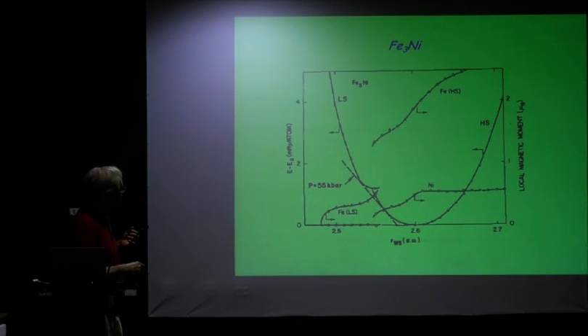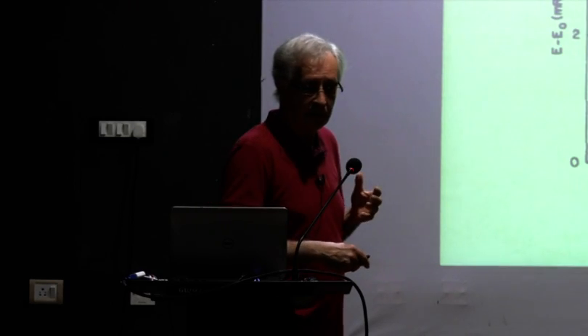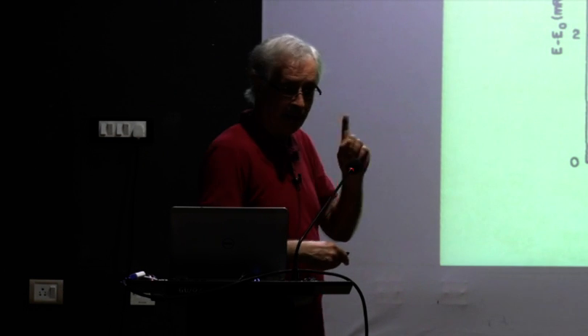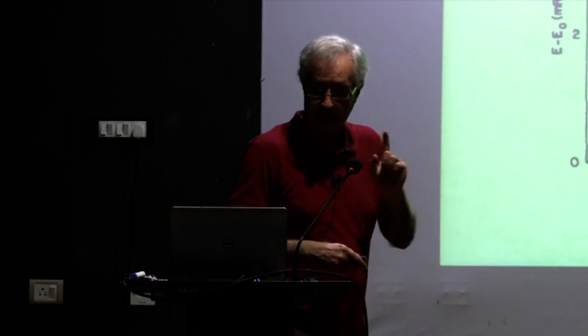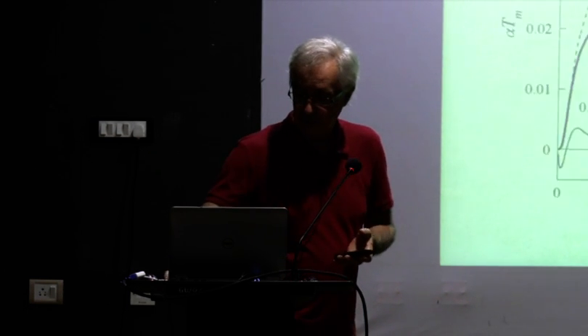And if we can compress this, if we go to smaller volumes, then we can go into a low spin state in this thing. So we have a discontinuity over here, and the energies involved between this low spin state and the high spin state is again in the order of 10 millielectron volts. But what has now happened? Things have changed around. Let's go back